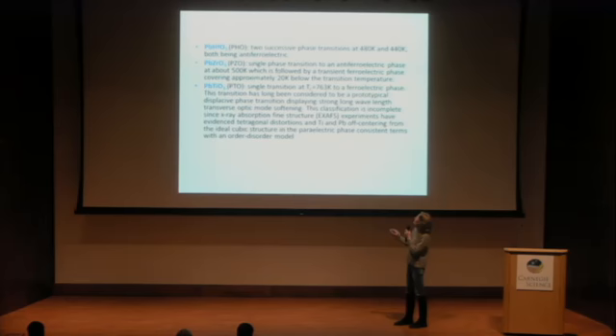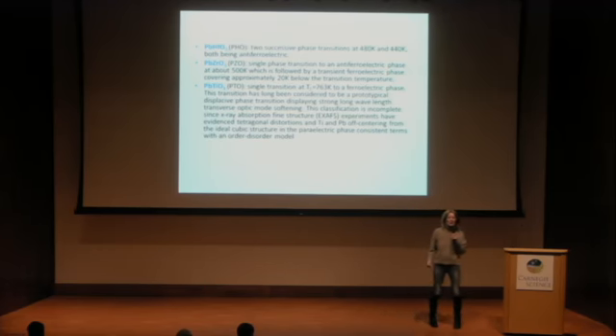These are well known, so in all these compounds you also have transitions from cubic to lower symmetry. Lead titanate is the only one which is ferroelectric at rather high temperature. Lead zirconate undergoes two transitions, to an antiferroelectric state rather similar to lead hafnate, whereas in lead zirconate one transition is a little hidden below the other one. I think we will hear about this later on. So these transitions are almost on the same order of magnitude and all are going to a polar structure.